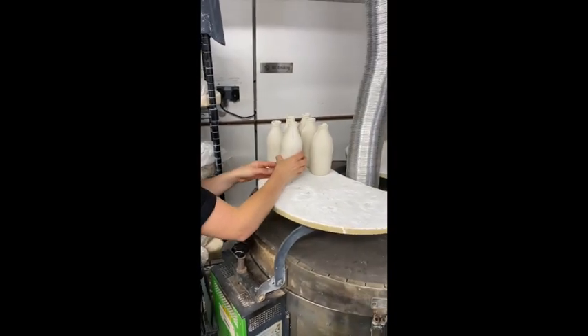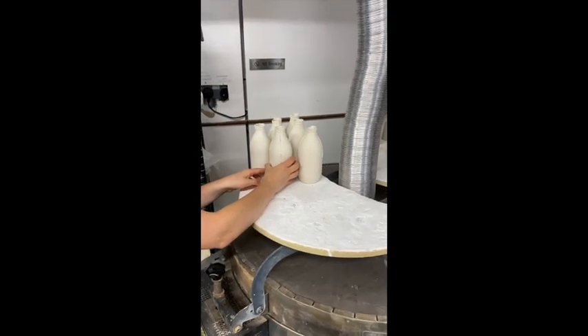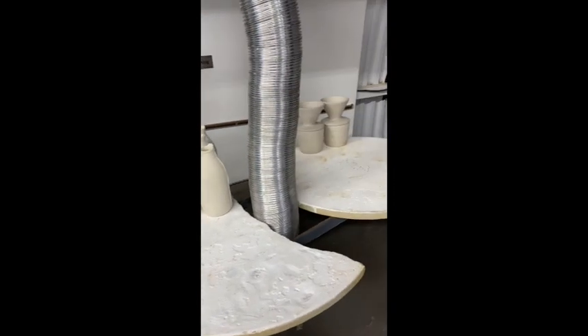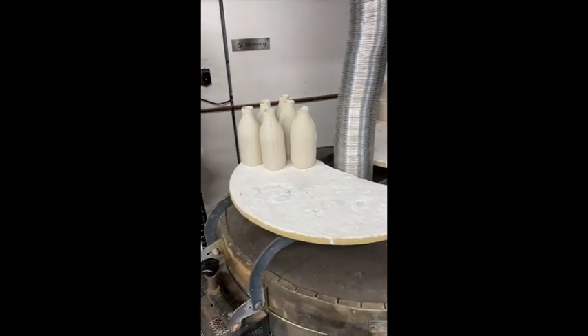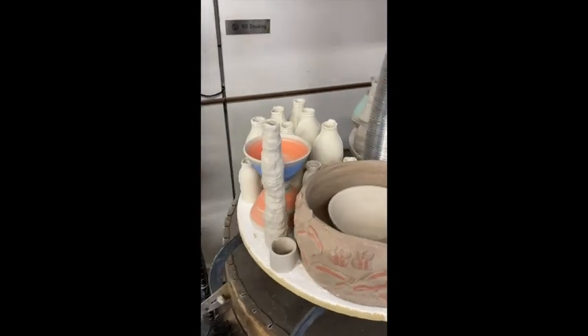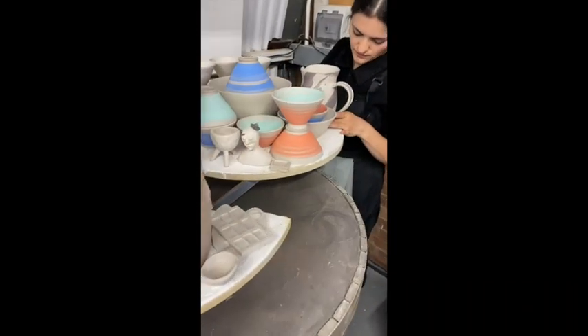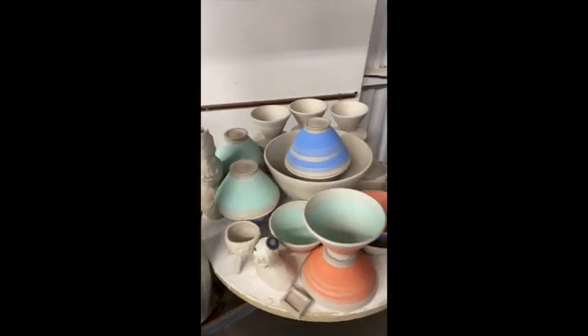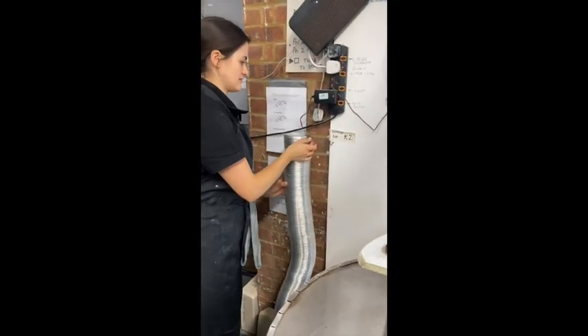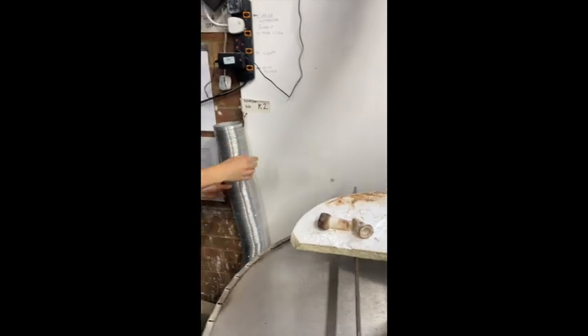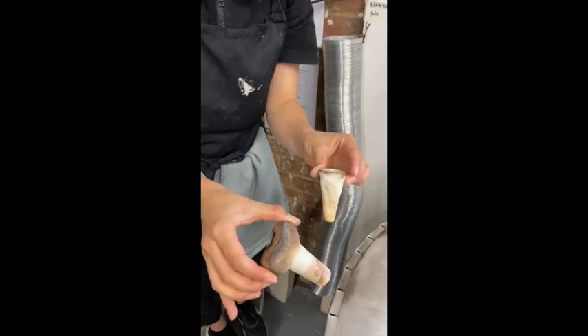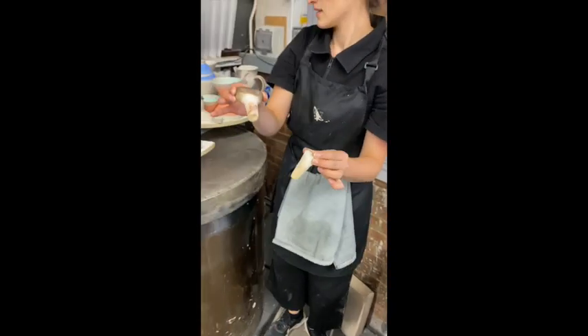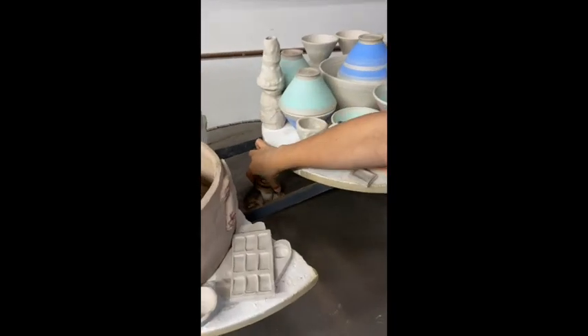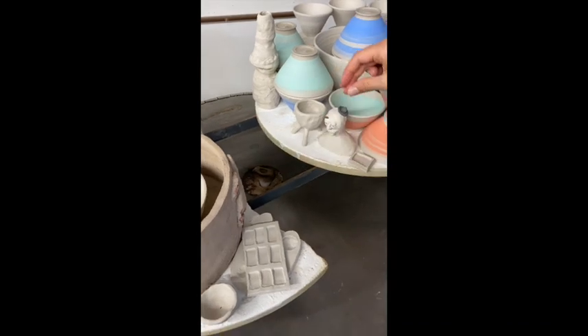Next, place half shells on top of the kiln and stack work that has begun to go off or dry on top of them. Do not put wet work on top, as this will make the drying process too fast and cause cracks in pots. Apply the same rules as packing a bisque when stacking these shelves. When the kiln reaches 400 to 600 degrees, it is time to bung it. All harmful fumes have now been burnt off, so we can remove the extraction tube and bung any holes that are allowing heat to escape the kiln. Try and bung the kiln closer to 600, although it is safe to bung at 400.